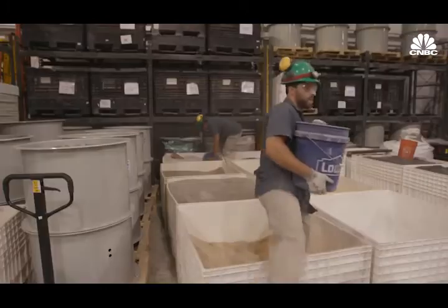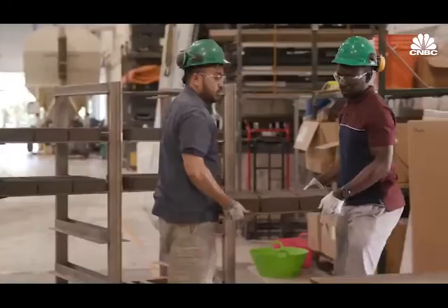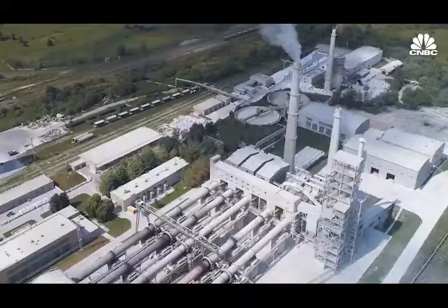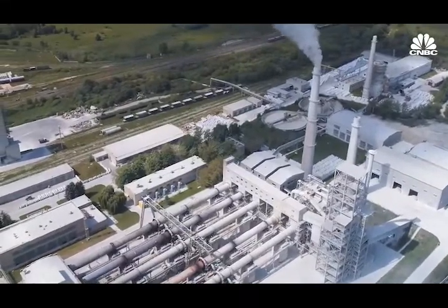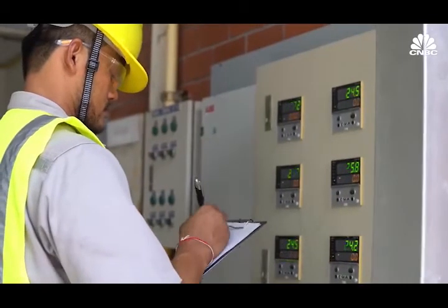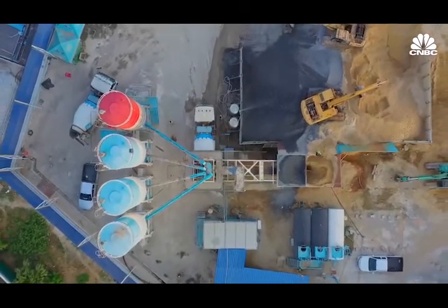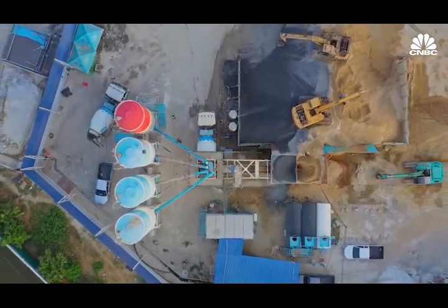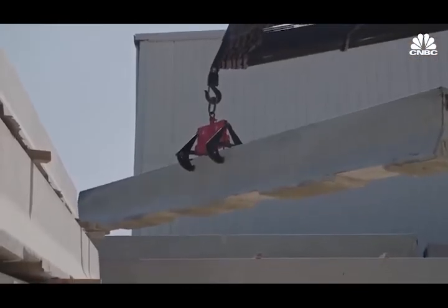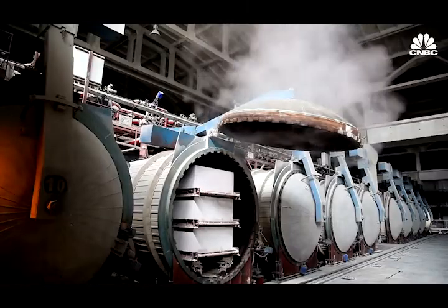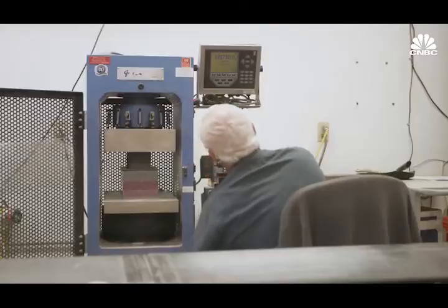We actually find that both on the cement side and the concrete side, if you use our technology, you actually end up saving money. Most of the cost associated with manufacturing cement is in the energy that you use, and we actually reduce that by about 30%, in addition to not having to use a lot of expensive raw materials that they use today. On the concrete side, they don't have a CO2 problem. They don't have a CO2 fee that's going to come attack them. So it really is about performance. And so for us, it's better colors. It's the ability to process it more readily. It's more durable. And instead of curing it in a week or 2 weeks or 3 weeks, it takes us 24 hours. So it's a lot easier for them to get it out in the market. So in the end, we actually are going to save the industry money.